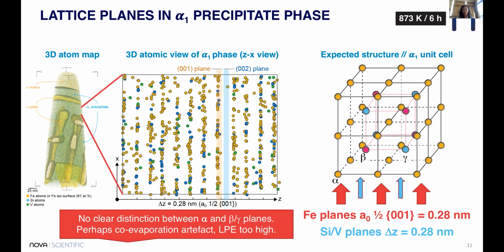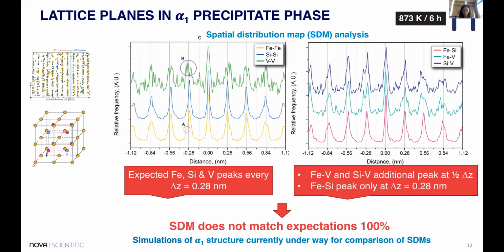For the same small volume with the lattice planes, we perform a spatial distribution map analysis as expected. For an Fe-Fe pair, we see iron interatomic distance with a periodicity of 0.28 nanometers, indicating that iron only occupies corner sites. Silicon shows the same periodicity, which we believe originates from silicon only occupying body center sites.